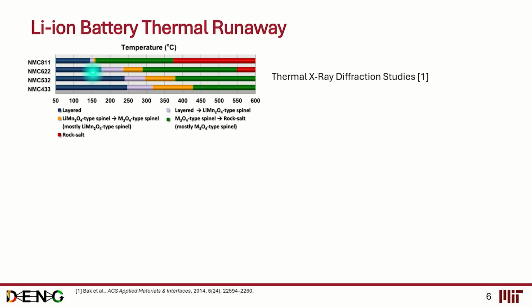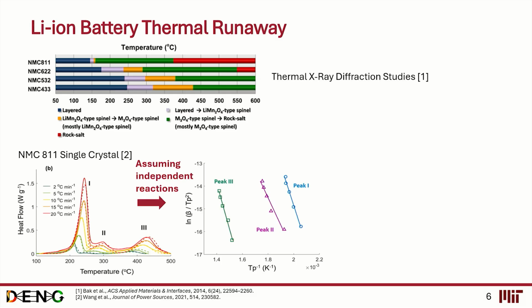And this step, depending on the chemistry, would happen at different temperatures, but the shared trend is that you need to have a 3-stage decomposition depending on the temperature. And probably the actual composition will delay it in certain ways. This is what the material scientists can tell us in the literature.